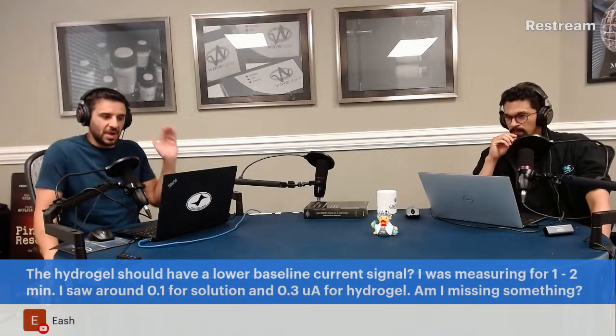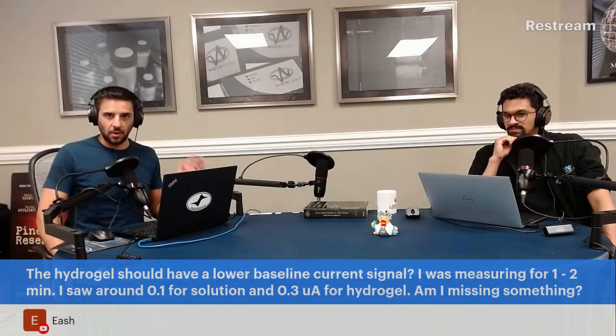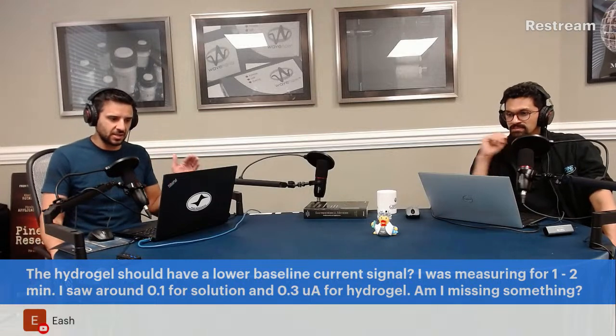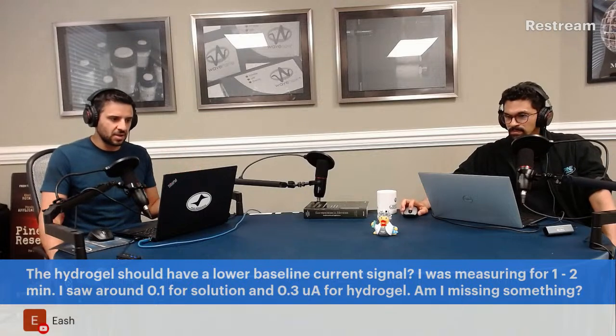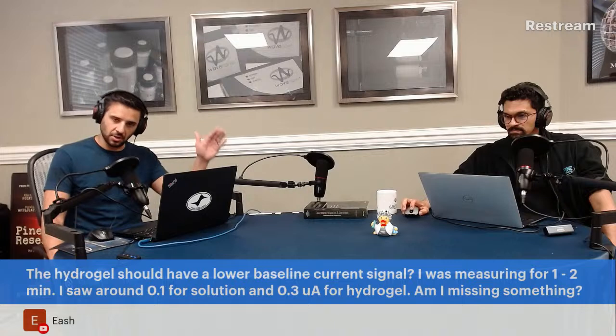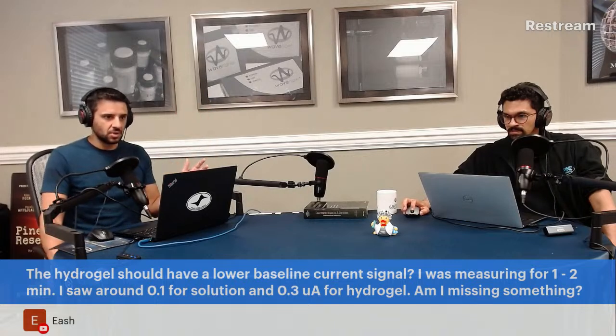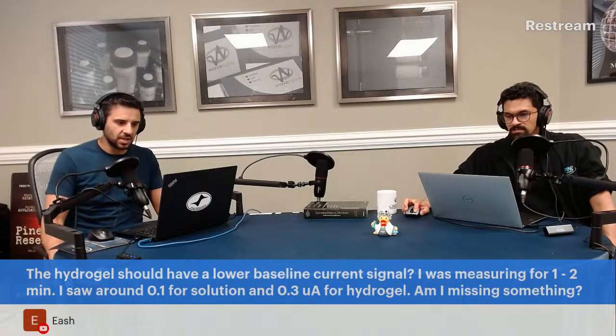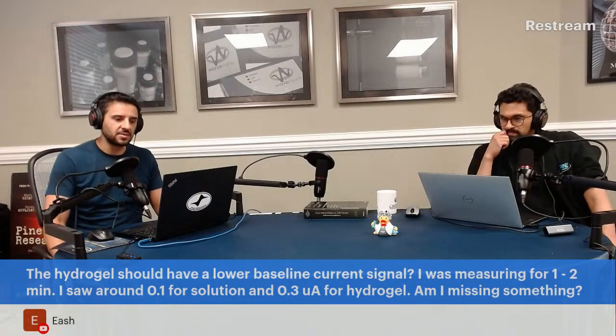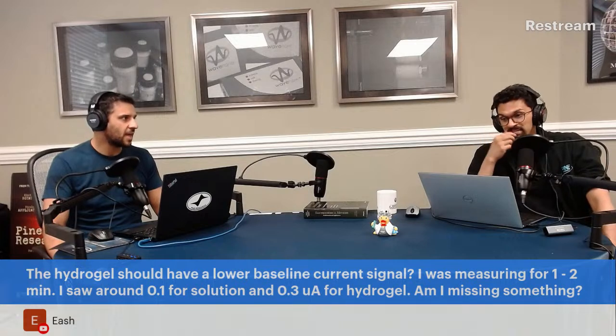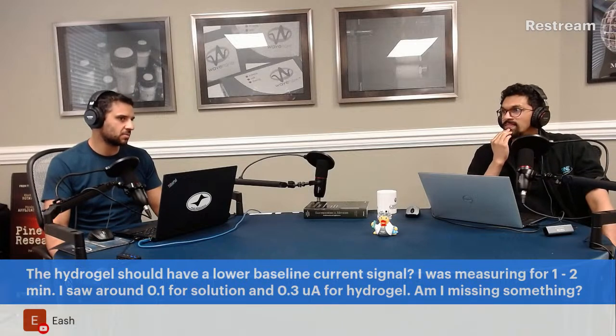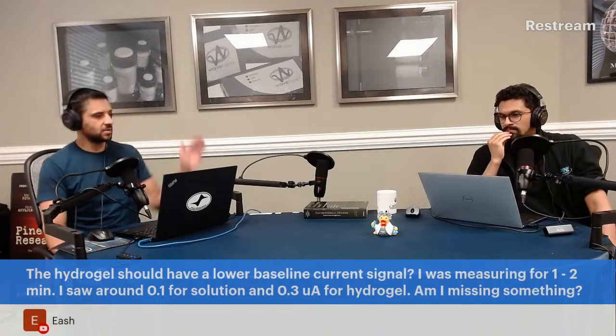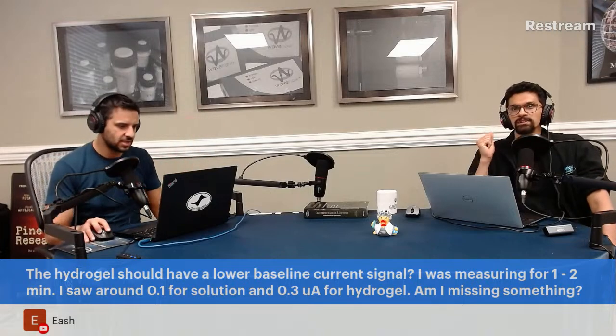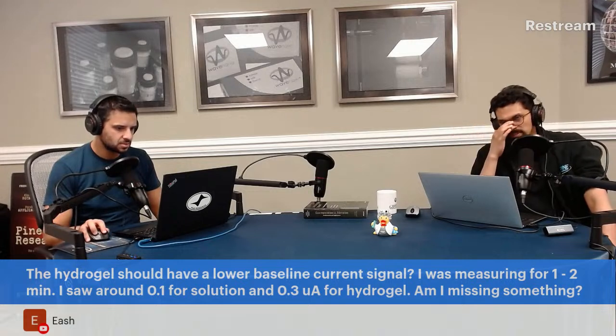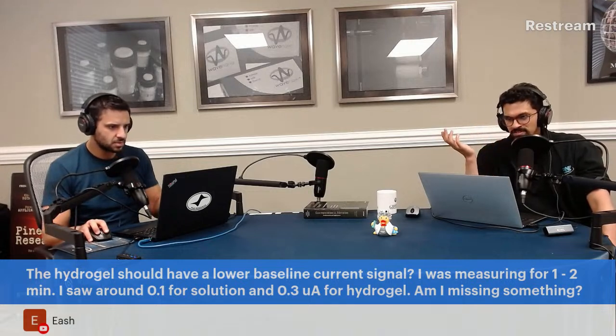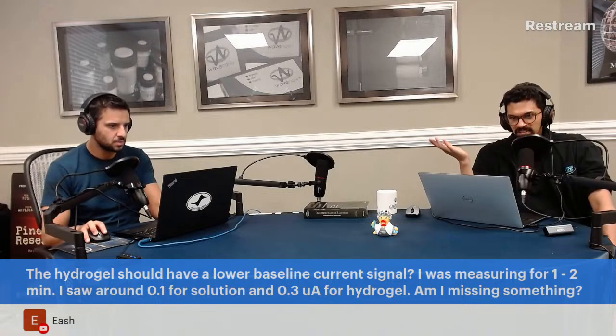That's one possible answer. The specifics might not work out in my favor here, but that's one possibility: that it appears over a short period of time because the time constant is larger. In other words, it takes longer to charge up the double layer in the hydrogel, so it has a higher current. And then over the long run, it should have a lower baseline because of the slower diffusion. But in the immediate,